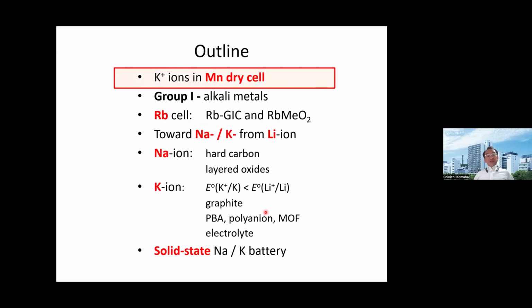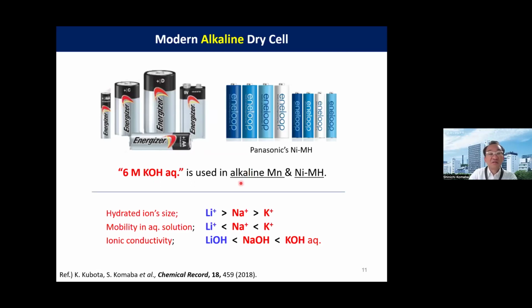So not only alkali metal comparison, we are already utilizing potassium ion in practical dry cells, such as manganese dry cells and nickel metal hydride. Maybe all of the audience today are battery experts, and everybody knows that 6 mol per liter potassium hydroxide aqueous solution is used for alkaline batteries because the hydrated ion size is smallest for potassium, and the mobility as a charge carrier is faster for potassium than sodium and lithium. So finally, the ionic conductivity is the highest for potassium hydroxide aqueous solution. So in order to minimize the internal battery resistance, potassium hydroxide is the best choice for alkaline batteries.